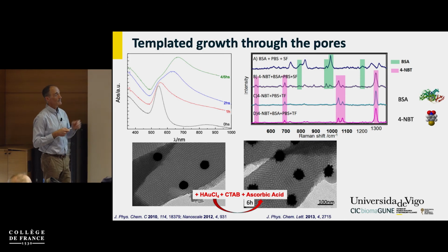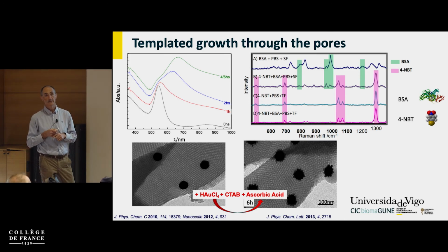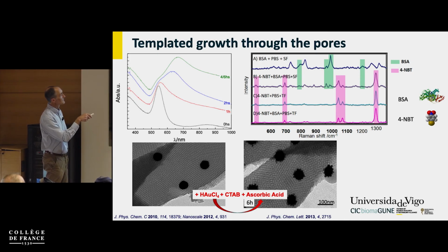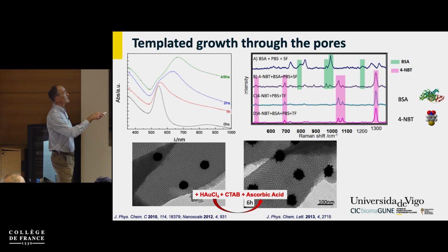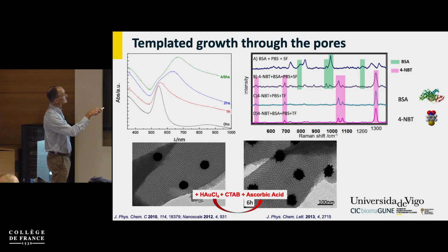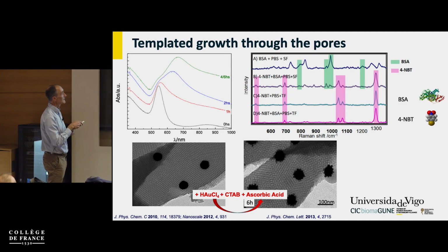And so then we asked Paula, what is happening here? And she said, well, maybe we are dissolving the silica by treating it with the biofluid, which is a well-known problem. And then she decided to do the same process by using titanium oxide rather than silicon oxide. And then it did work. And so this is only 4-NBT in PBS with the titanium oxide film.